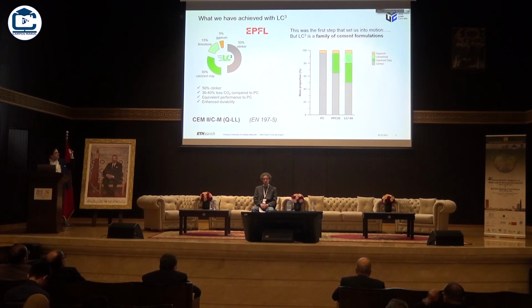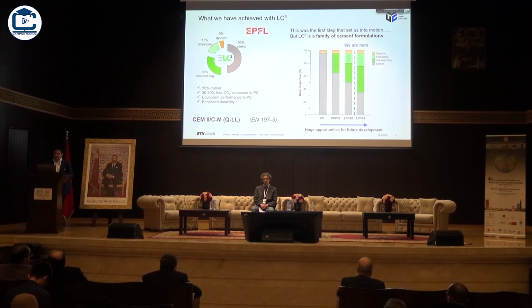So, while this is the typical combination or recipe to make LC3 that we tend to show people, it's important to realize that LC3 is really a family of blended cements, and these proportions of limestone, calcined clay, and clinker can be adjusted in order to get the properties that we need for a particular application. So we are basically here in what we call LC3-50, 50 standing for this 50% clinker factor, but I see significant opportunities for going even further in the reduction of clinker content, and this avenue is basically enabled by the high reactivity of calcined clays. And I would like to show some results and some thoughts in this direction during the presentation.